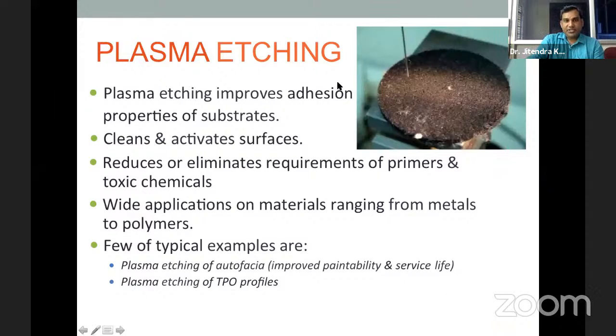Another kind of method which is used is the plasma etching process. By using this method over the surface, we can improve the adhesive property of the surface. So first what we do is clean and activate the surfaces by this plasma etching process. If you want to clean your surface before coating, the oxygen plasma cleaner: you send your sample, cleaned with acetone, into the plasma cleaner, and the plasma cleaner cleans the foreign particles by directing the plasma over the surface, and it can also generate the OH group over the surface. So that improves the adhesive property, and when you apply some coating, it can easily adhere if you have applied this etching process properly.